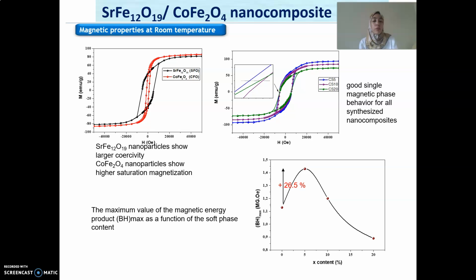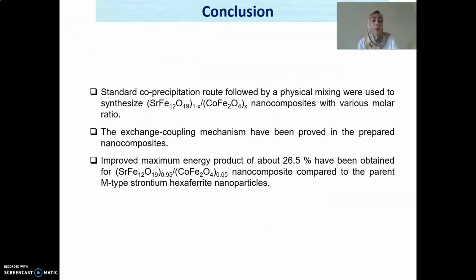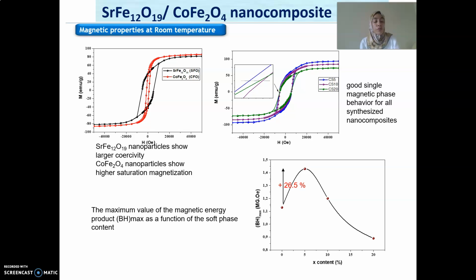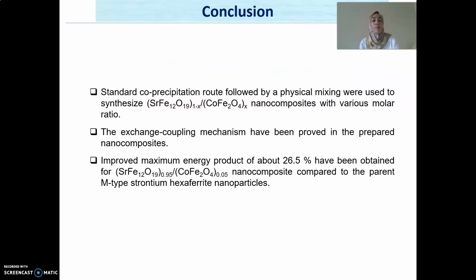And to evaluate the performance of the prepared samples for permanent magnet applications, we plot the maximum energy product as a function of the soft phase content. We can clearly see an enhancement of about 26% of the maximum energy product for 5% of the soft phase compared to the pure hexaferrite phase.